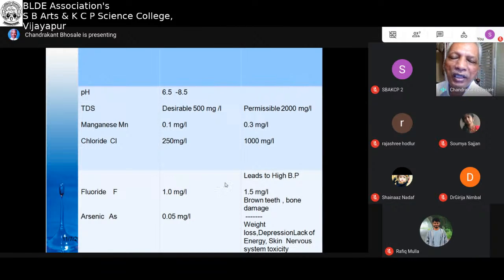For potable water, what we require is that pH should be 6.5 to 8.5 in this range. You know, normal water has pH 7. So mostly we require alkaline water. The total dissolved salts are permissible up to 500 mg per liter, and the maximum permissible quantity is 2000 milligram per liter. Manganese, if it is present in the water, you can have 0.1 milligram per liter, and at the most you can have 0.3 milligram per liter.